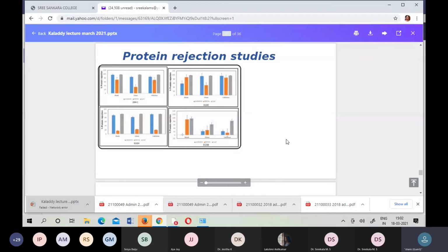So something has to pass through the membrane surface and come out, which means you need to have the pores and morphology retained, whatever you made initially. So the thin coating, and we did the same with water. We did clay; we sent different concentrations, like 1000 ppm and 500 ppm, and different proteins, bovine serum albumin, so different